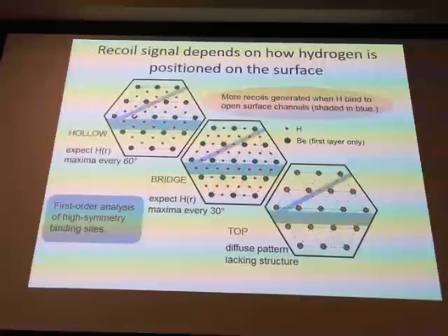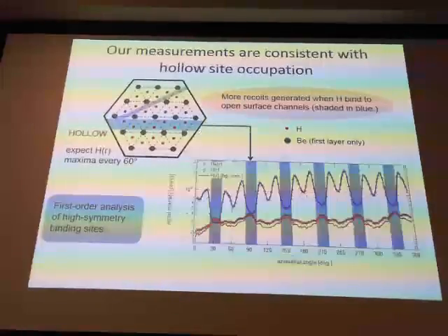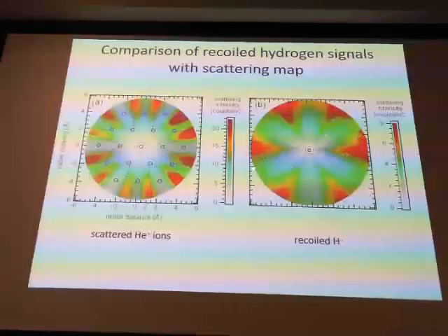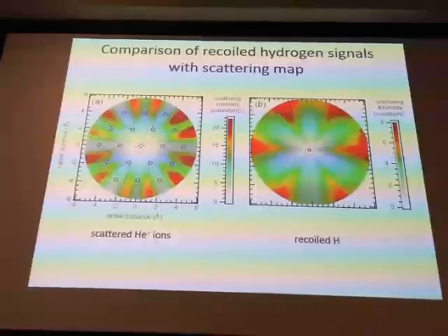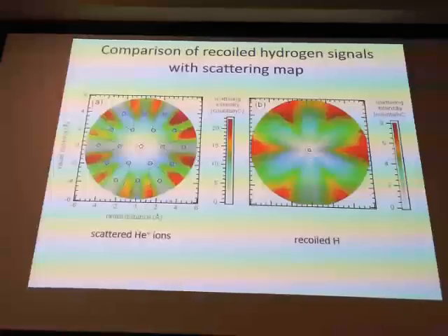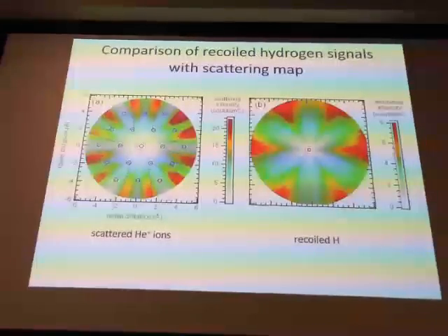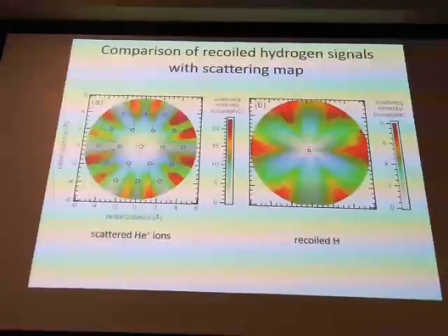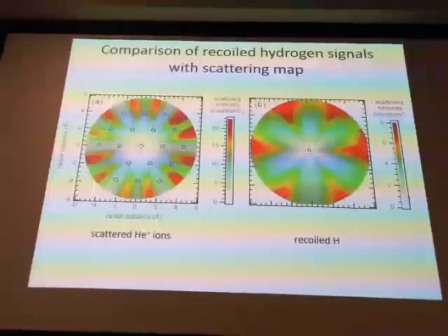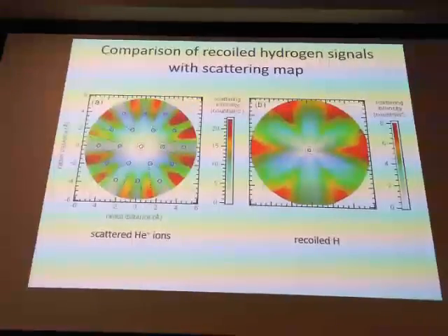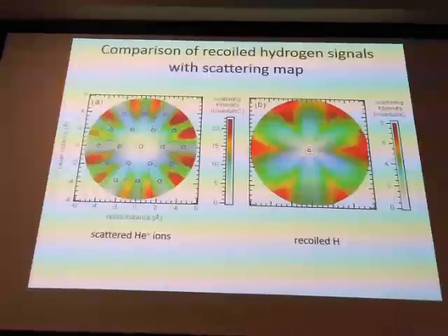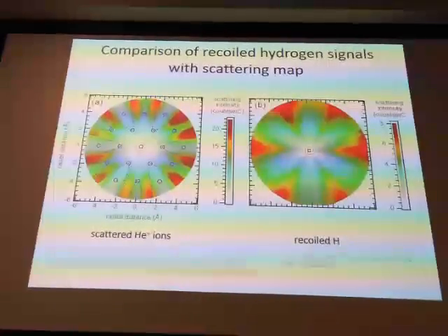If hydrogen is present within the surface channels, you get a different symmetry to your hydrogen data as a result. And so what we find here is that the data is actually consistent with this hollow site binding, and so it provides a direct identification for where the hydrogen is actually binding on the surface. And then, using molecular dynamics models, we can actually simulate our scattering data and then get a direct determination of the height of the hydrogen and basically the bond length relative to the neighboring beryllium atoms, and directly identify where it's sitting on the surface. So this is more of a fundamental science study that we've undertaken at the lab.